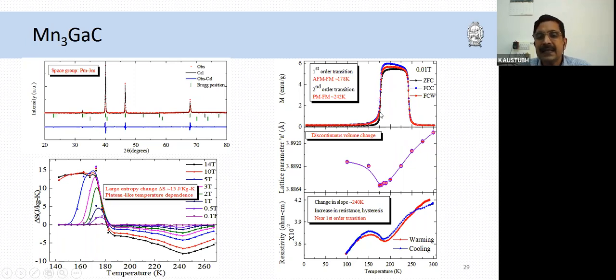Kelvin. At this transition, you can see that the unit cell volume, which decreases, suddenly shows an increase, and then the lower antiferromagnetic state has a higher volume than the ferromagnetic state at this temperature. And the same behavior can also be seen in resistivity, which shows the hysteresis behavior and the first order transition.